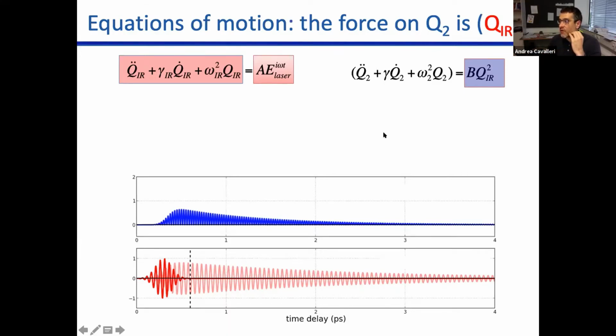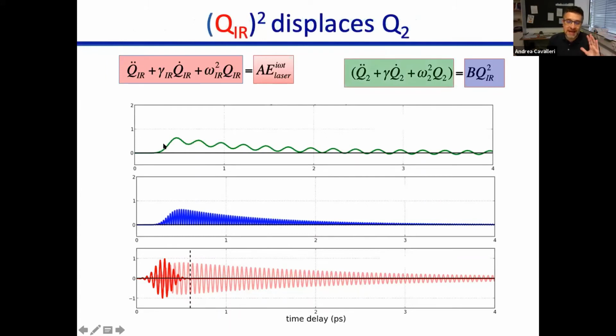And because the force is proportional to the square of a sinusoidal wave, whilst the directly driven mode oscillates about an equilibrium position, the force that acts on the second mode will be proportional to the square of sine, which now has a direction, and therefore the mode will be displaced.